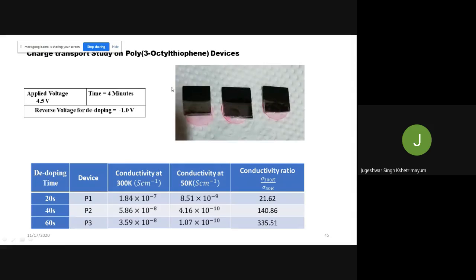Here, unlike the methyl thiophene, the monomer concentration of octyl thiophene is increased from 50 millimolar to 140 millimolar. Now, after preparing, we measure the electrical conductivity of the P1, P2, P3 devices. We prepare the film and de-dope for 20 seconds, 40 seconds, and 60 seconds de-doping time. So with very little de-doping, the charge carrier concentration is higher; the longest de-doping gives the lowest charge carrier concentration, and the other is moderate. So these are the conductivities of the samples P1, P2, P3.